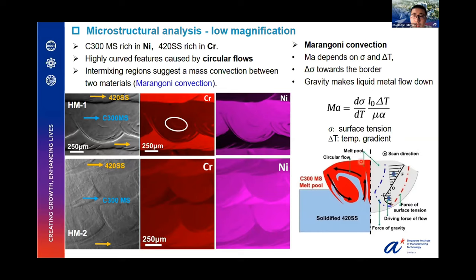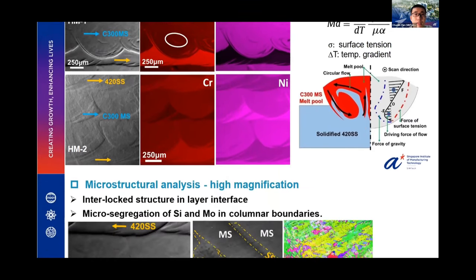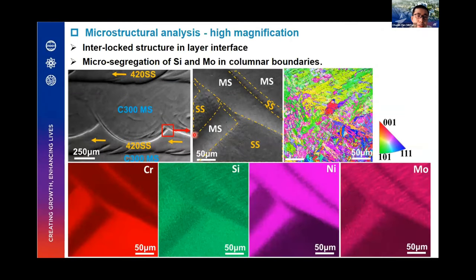Specifically, the temperature gradient causes surface tension from the center of the melt pool to the boundary, and gravity drives liquid flow down to the bottom of the melt pool, forming a circular flow that brings bottom material into the top material as an intermixing structure. High-magnification observation of the interface reveals an interlock structure at the layer interface, which is beneficial to interfacial bonding. Micro-segregation of silicon and molybdenum along the columnar boundary is also observed.